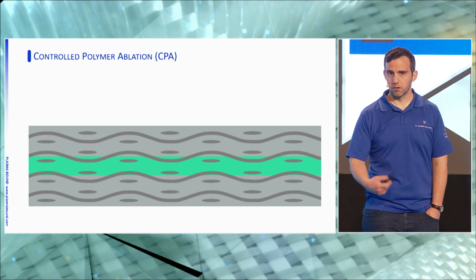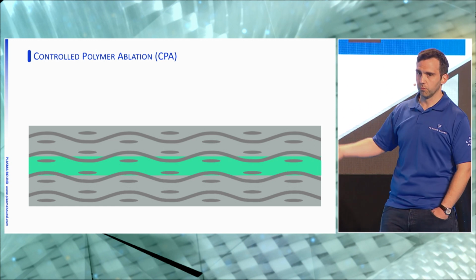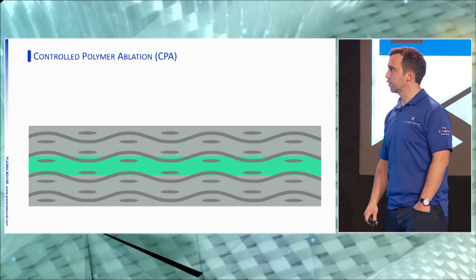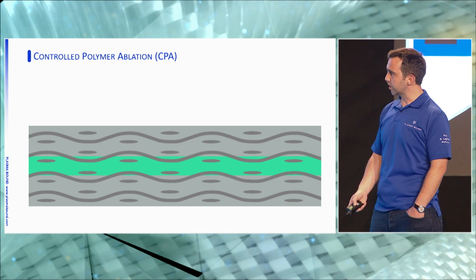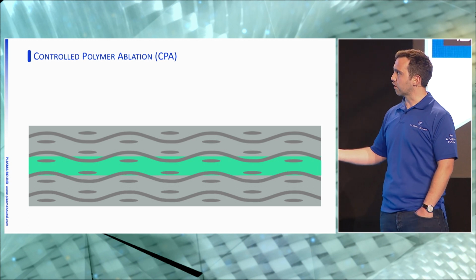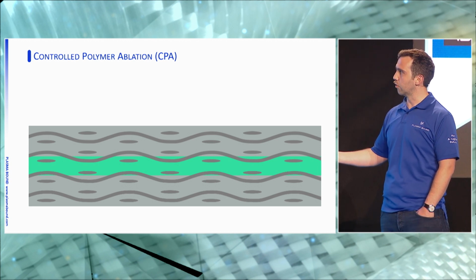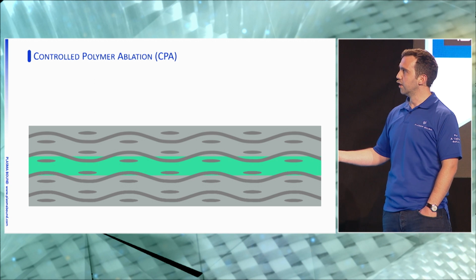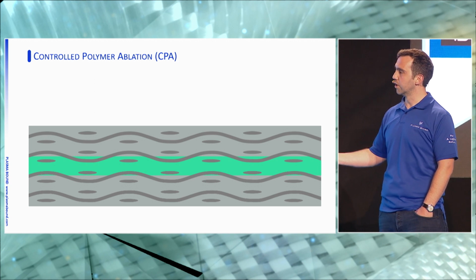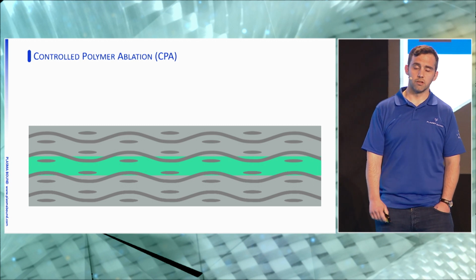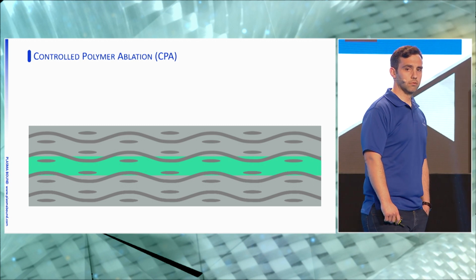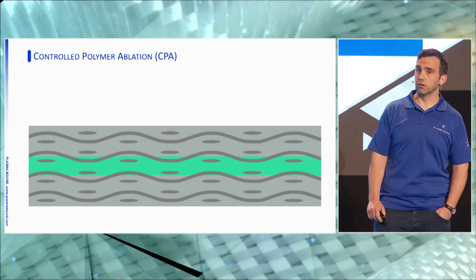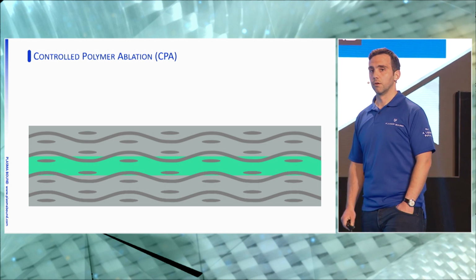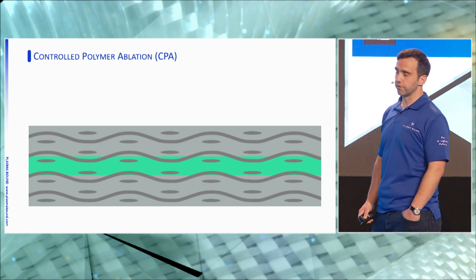This could be metal, this could be glass, and it could be composite as well, it could be polymer. Whatever you want it to be. But the main point is that now what you can see across here is certainly the interface is no longer as easy to define. The adhesive will see fiber structure, and what you end up with is essentially a fiber reinforced bond joint, which is considerably tougher or stronger than the original option, which was a roughened surface or a peel ply surface.